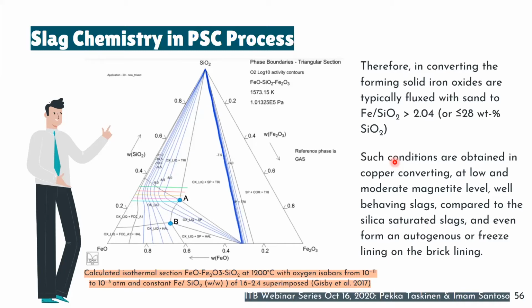This slag can also form a freeze lining on the brick lining. So the slag can be very protective to the brick. So the shutdown of the furnace can be delayed because the brick can run longer, because if the slag forms during operation, it forms a protective layer for the brick, and it can protect the brick from the aggressive attack of the slag.